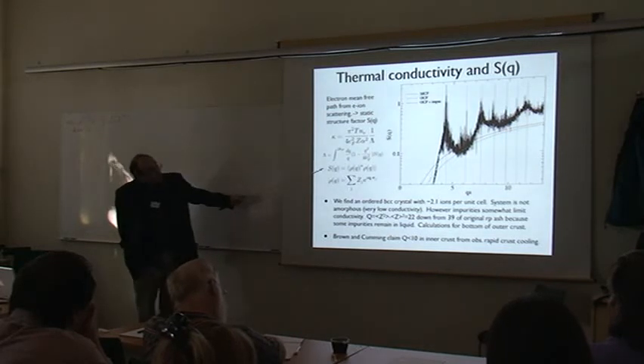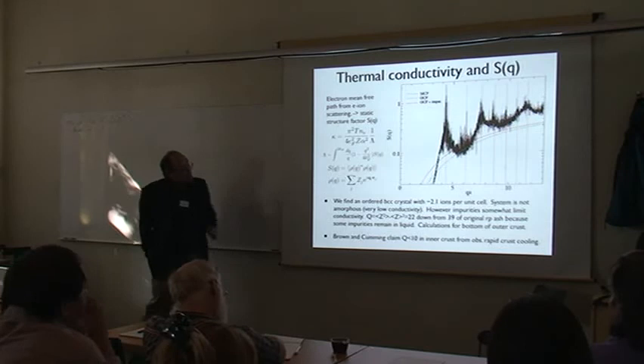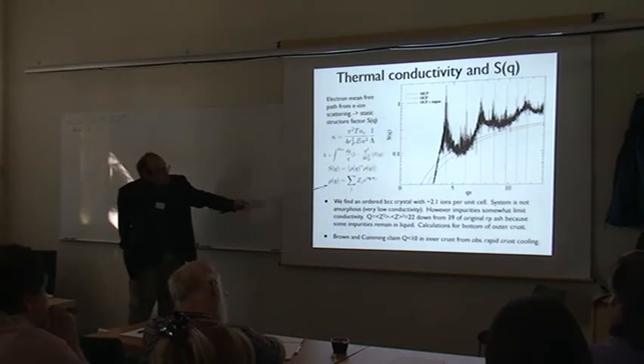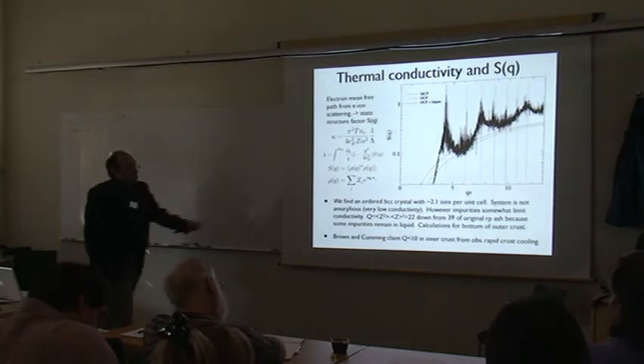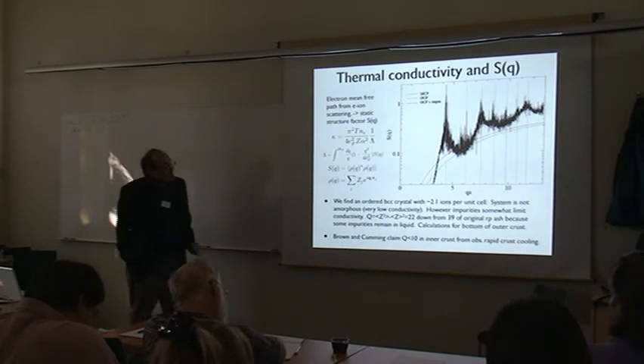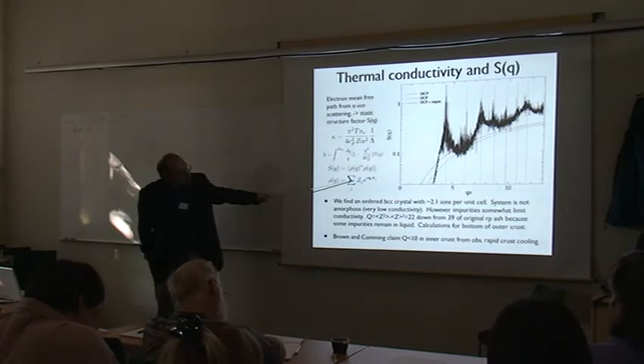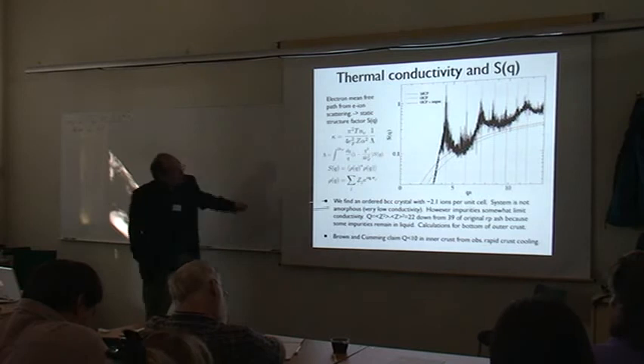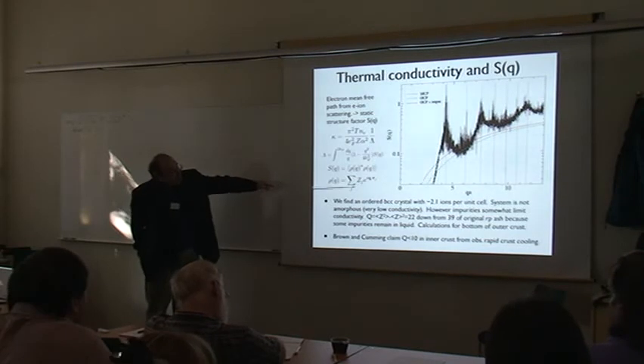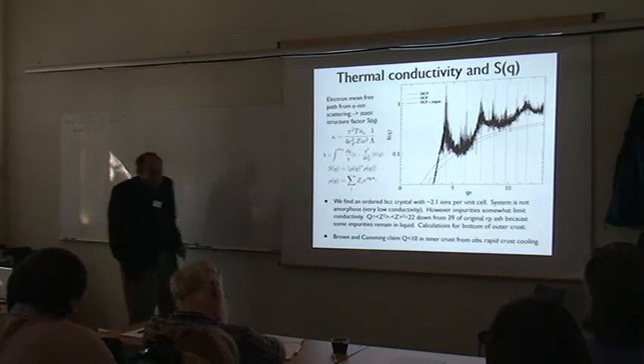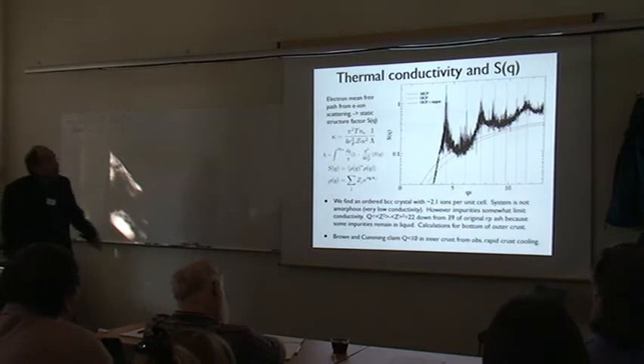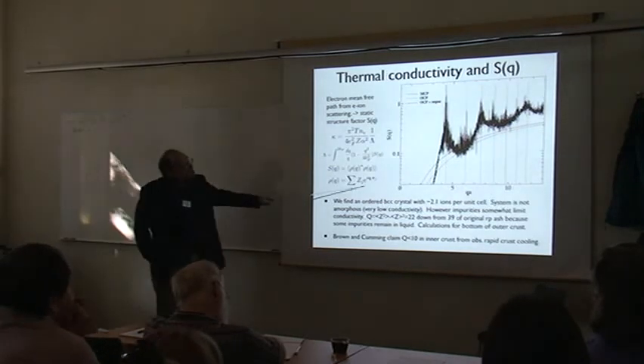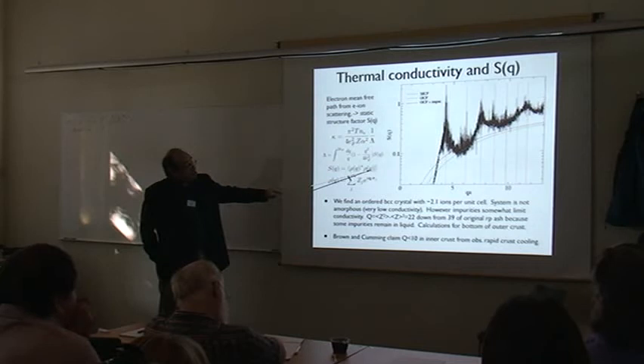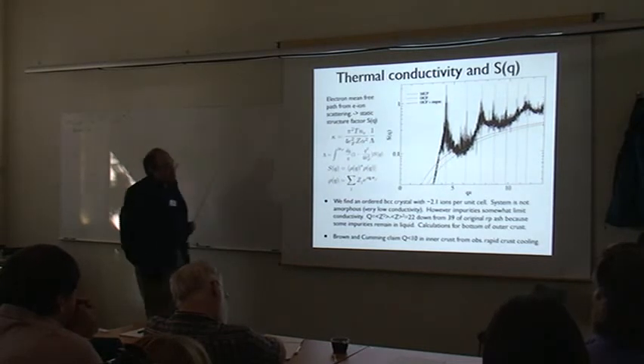So a little bit of terminology: it's a density-density correlation function. This is the charge density of the ions, so you're just summing over all the ions. This simulation had 27,000 ions, so you sum over the coordinates of each one, and it's just that Fourier transform gives you the density. You calculate that at one particular time, and then you average over all times to get the static structure factor.